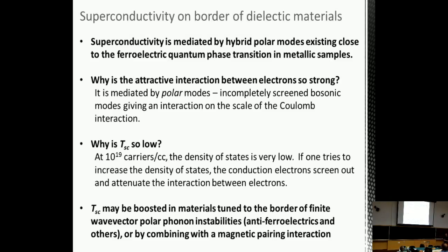So just to recap, superconductivity seems to be mediated by hybrid polar modes, which are the coupled degrees of freedom of the electrons and the ions, and maximized close to the ferroelectric quantum phase transition. Why is the attractive interaction so strong? It's because the bosons are polar. They're charged objects which are not screened out by the conduction electrons. So the electrons feel an interaction on the scale of the Coulomb energy. And why is Tc so low? Well, that's because the density of states is so low. And if you increase the carrier concentration, then the electrons screen out the interaction and make it weaker.